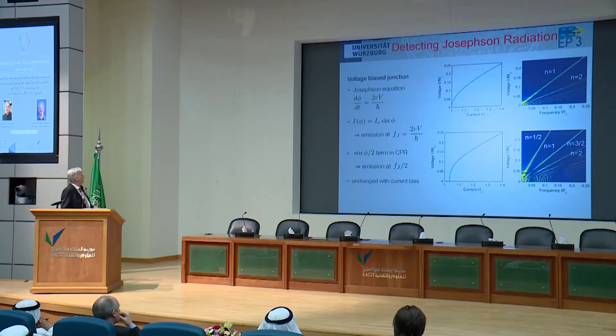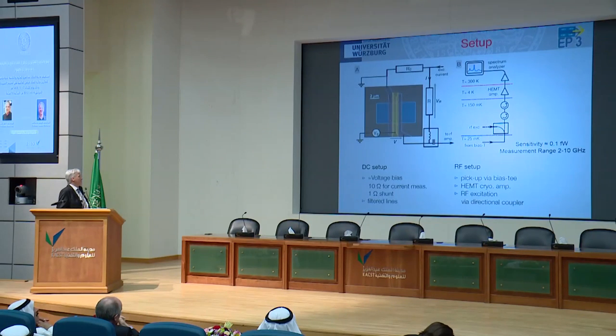And the final experiment we do there is actually a somewhat simpler experiment to understand, but difficult to do. We look at the Josephson emission. So basically you bias your Josephson junction out of superconductivity, and you look at the noise that comes from it, and you have to hope to pick up the Josephson frequency. And of course, the Josephson frequency for the zero mode has half the frequency compared to all the normal modes. And we do a pretty simple experiment again. So we bias all in DC, and we have a bias T to take out the AC for the spectrum analyzer, and we amplify it and put the noise in a spectrum analyzer.